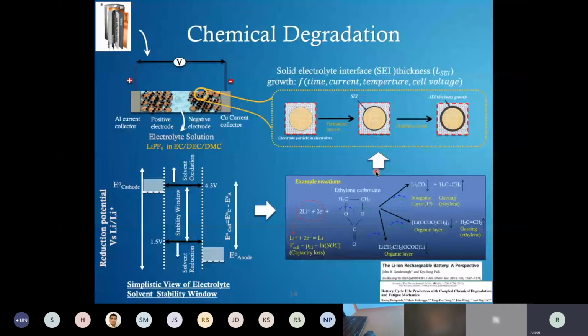This is similar to oxidation of metals when they are in air. There is an oxidation layer on, let's say, iron or copper if you just put it in normal air. These are similar products which form a layer. Once a layer is formed, it reduces the rate of reaction because of the distance between them. So they form a passivating layer, and the electrolyte is not in direct contact with the electrode anymore. So they reduce the rate of reactions, but the reactions are not totally stopped.